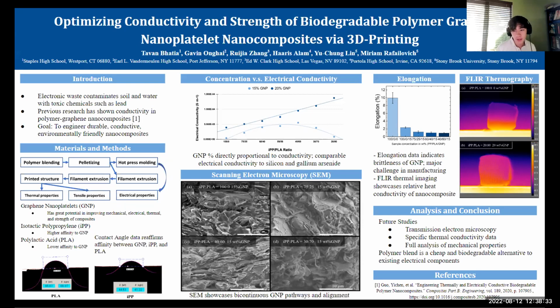First, we blended polylactic acid, polypropylene, and graphene nanoplatelets in a polymer blender. From here, we could either thermopress it, which gave us a rectangular prism, and then we could test the electrical conductivity using that. We could also 3D print a dog bone shape, allowing us to test the tensile strength. And we also printed 3D cubes, which we used the FLIR thermal camera on to measure the thermal conductivity. We used a scanning electron microscope, or SEM, to examine the cross sections of each sample. Lastly, we measured graphene's affinity for either polypropylene or polylactic acid using contact angle imaging.